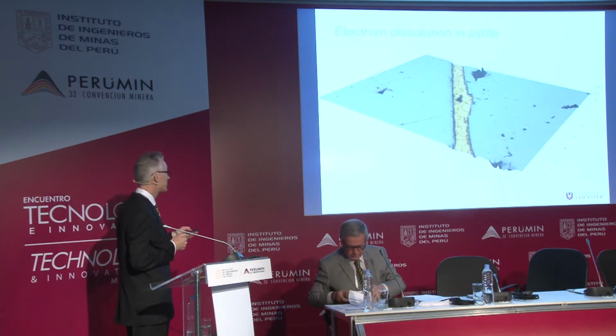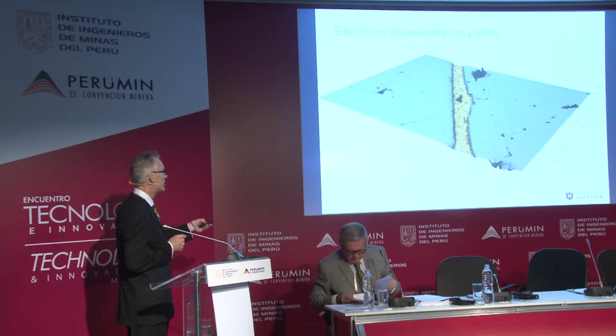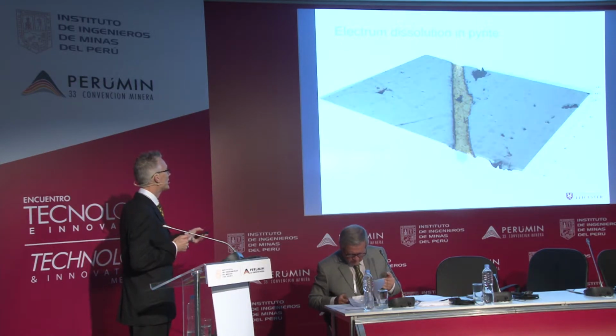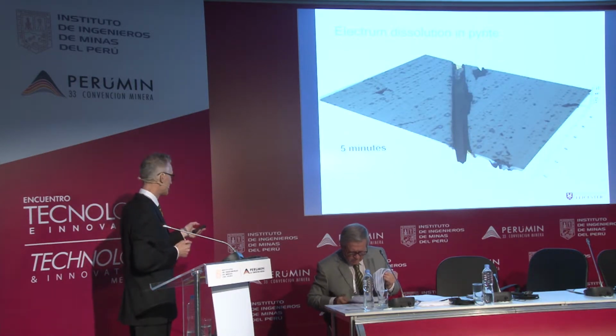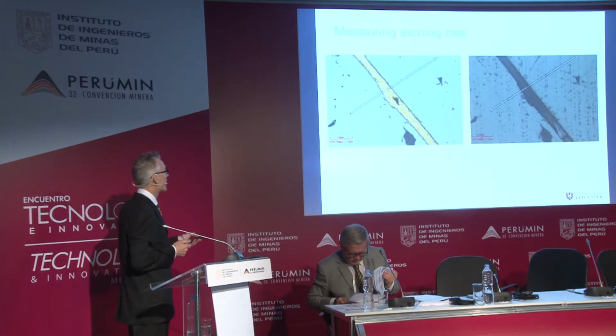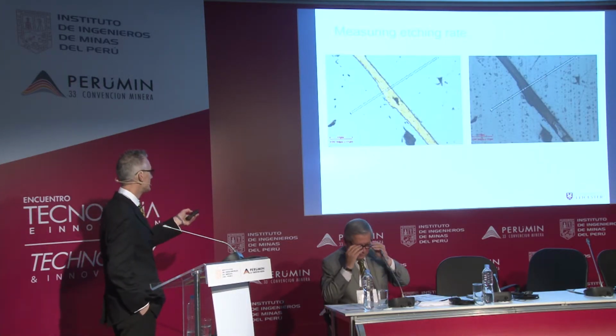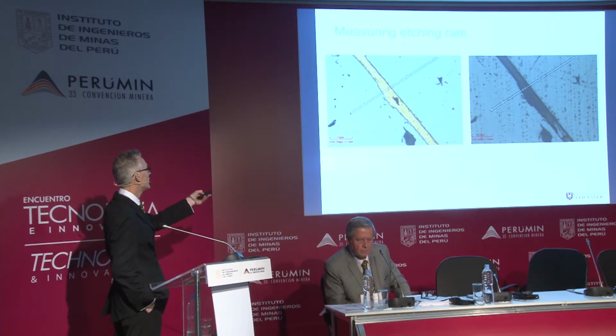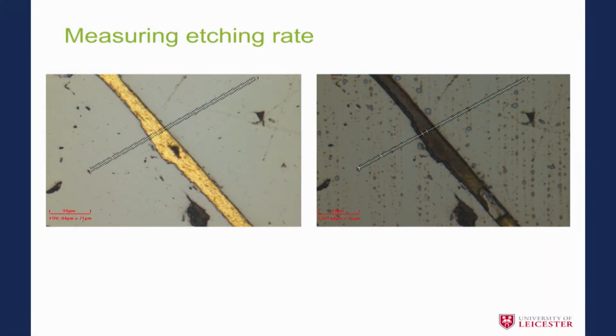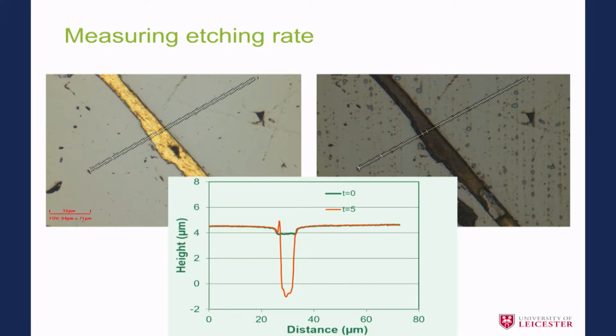Okay, here's another example. So we have pyrite and electrum filling a fracture. After 5 minutes, the electrum has dissolved away. If we look here in a plan view, we take a profile across the surface before and after, and we compare the two, and we can then subtract one profile from the other. Note the initial profile, there's a depression where the gold is because of the polishing. We subtract one from the other, and we can work out how much gold, what depth of gold has dissolved in 5 minutes.